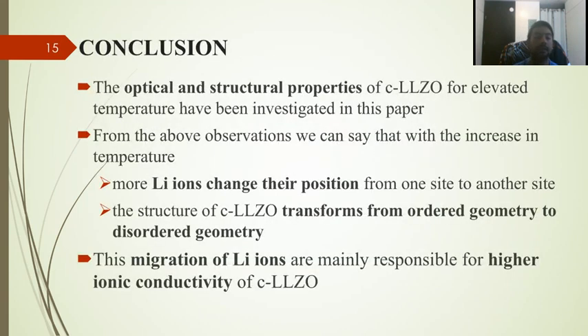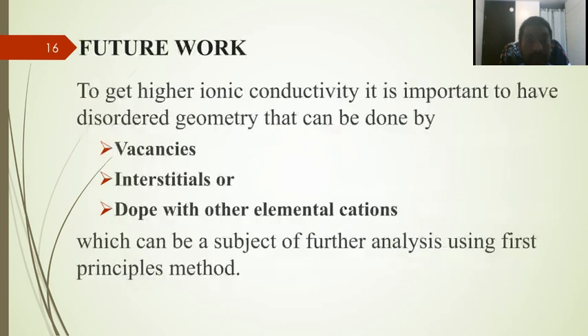So in the conclusion, we can say the optical spectral property is very important to investigate. And from this investigation, we can say the lithium ion is changing their position from one site to another site. And because of that, the ordered geometry of the cubic LLZO is getting disordered. And because of this migration of lithium ions, conductivity of cubic LLZO is getting higher. Next.